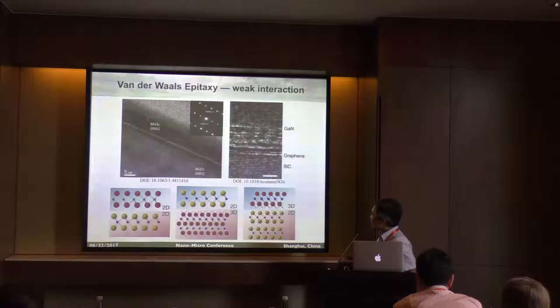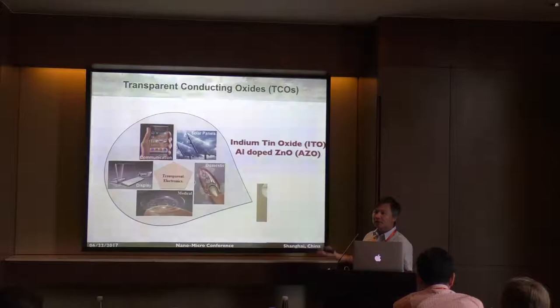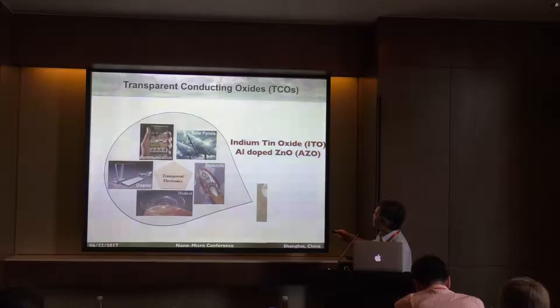In my study, we take the muscovite substrate and put down three-dimensional functional materials on top. Now that we have the substrate, we also need electrodes. For the electrical electrodes, we picked two materials: one is ITO, and another one is aluminum-doped zinc oxide (AZO). We deposit the ITO and AZO on top of muscovite. You can clearly see all these X-ray peaks — one coming from ITO and one from AZO, and this is the muscovite substrate.